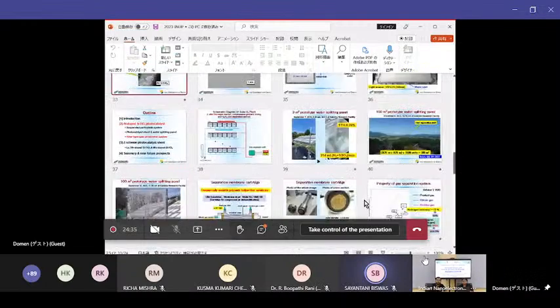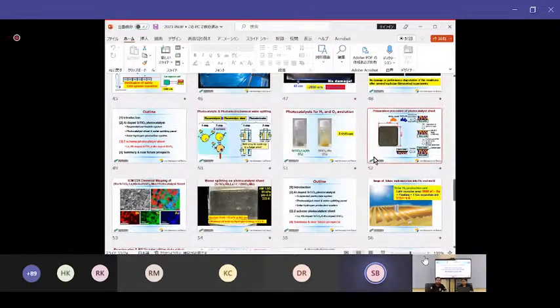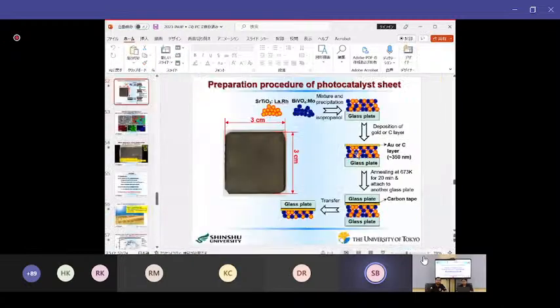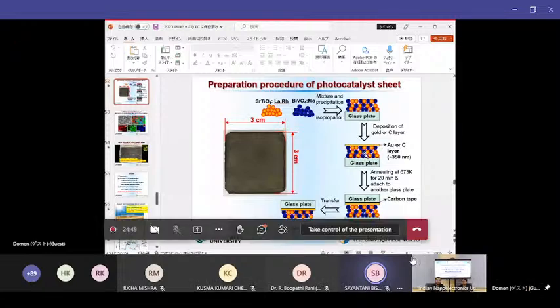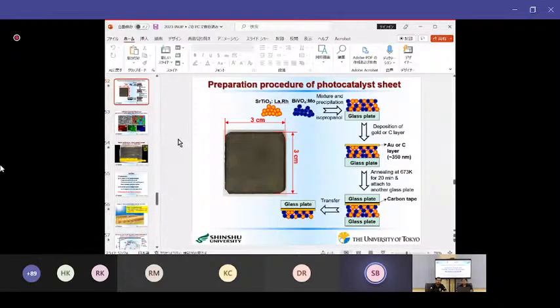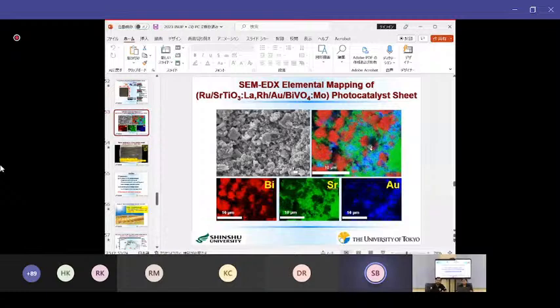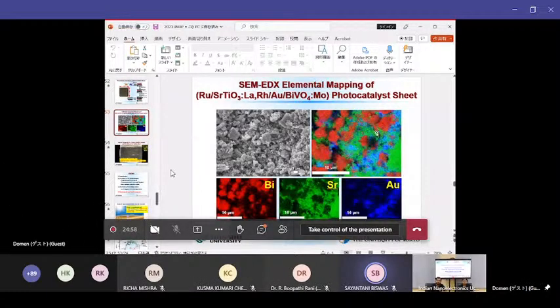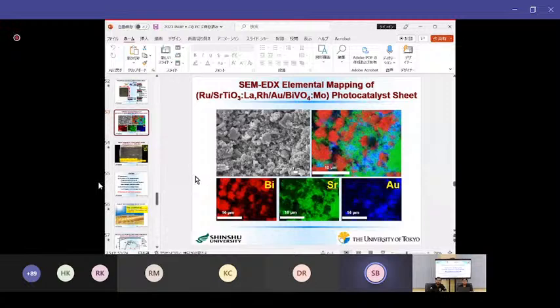And in the case of this Z-scheme water splitting system, it is also less than 10 micrometer, several micrometers thickness. But I should say that in this case, if we can make a more well-ordered structure, probably the activity or quantum yield will be improved more. At present, our quantum yield was about 30%. So to get 50% or 70% quantum yield, we need to make a more well-ordered photocatalyst sheet.